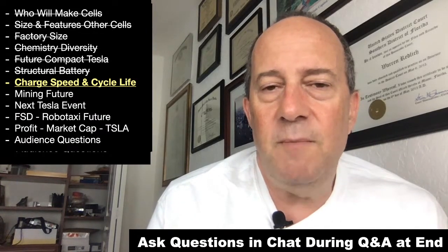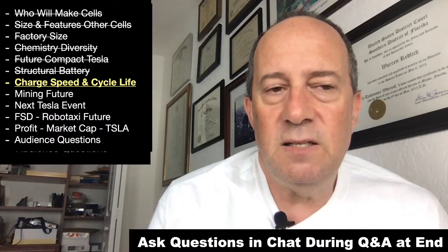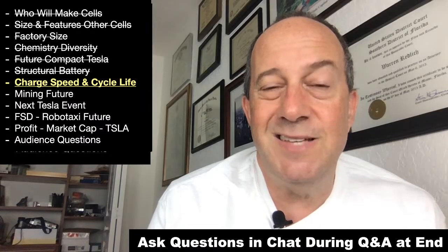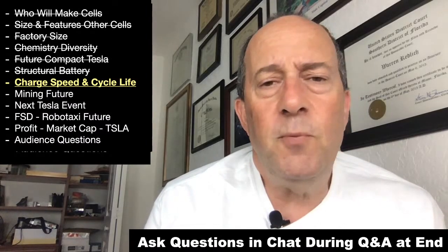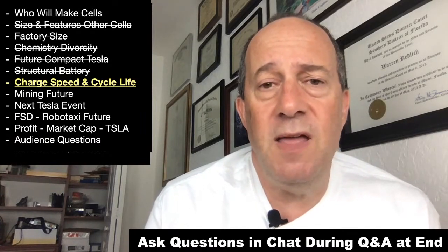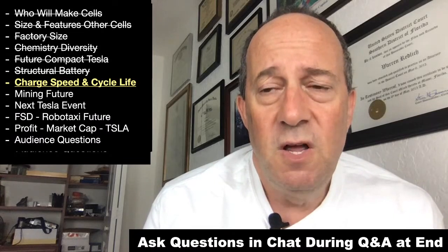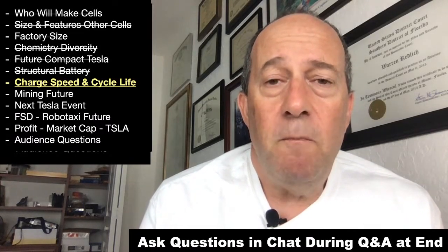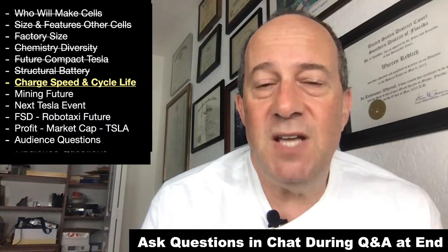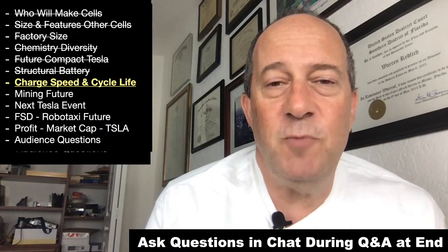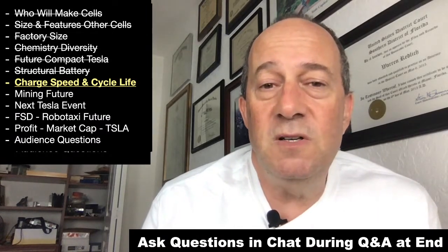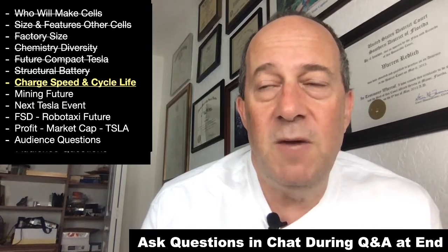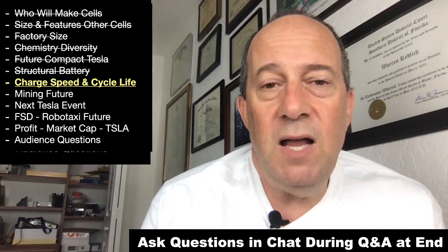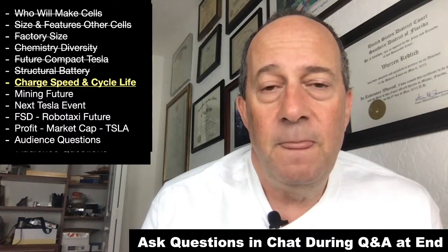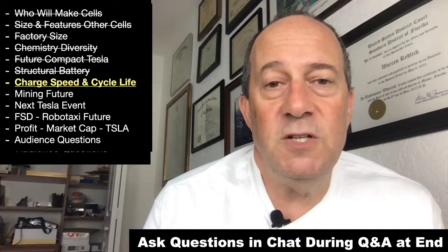It sounded like the combination of the larger format cell, the silicon anode, and the high nickel cathode is going to have significantly higher energy density. From previous tweets from Elon, he said in 3 to 4 years they expect to get to 400 watt hours per kilogram manufactured, which would be the high nickel batteries. Since they've said cell energy density improves about 5% a year, and this is a step change, my hunch is they're going to go from the 260 watt hours per kilogram they've got now with nickel cobalt aluminum to 340 watt hours per kilogram with the new high nickel chemistry. Then 1.05 to the third or fourth power gets you close to 400 watt hours in 3 to 4 years.